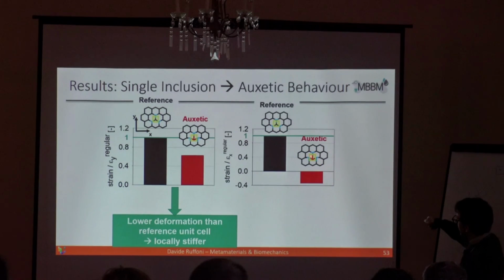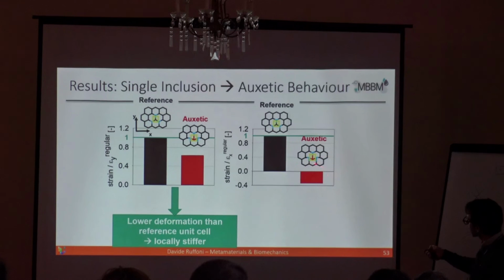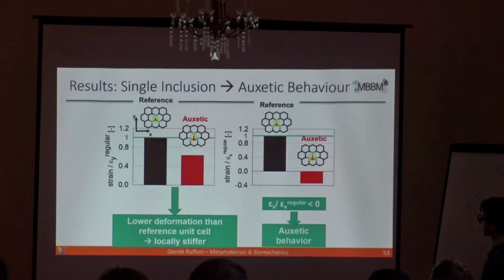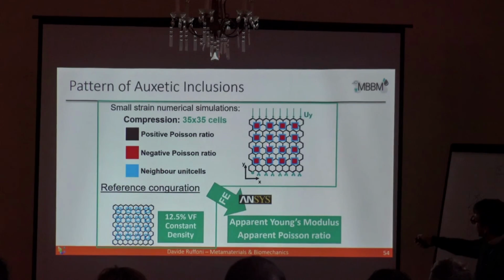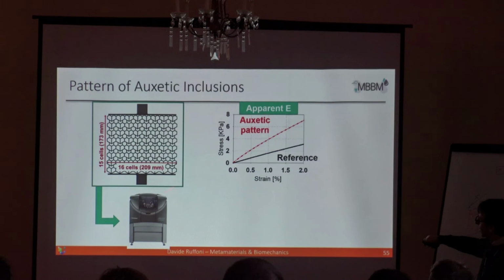So this means that just a single auxetic inclusion in an overall positive Poisson ratio lattice is able to retain its behavior. And this was already a little bit interesting, to say, okay, just by perturbing this geometry, I can retain the negative Poisson ratio behavior. And then the idea is to introduce a pattern of inclusions and to see the behavior of this lattice, both with simulation and with experiments.